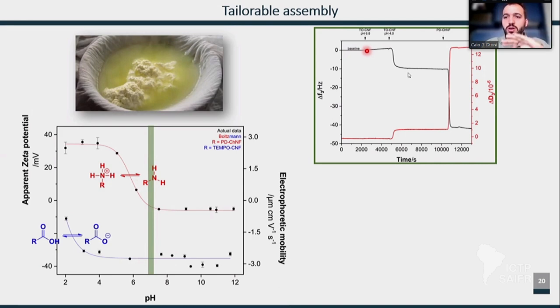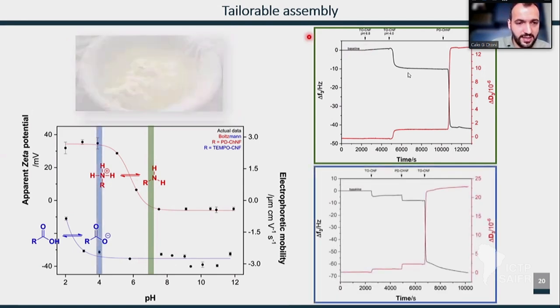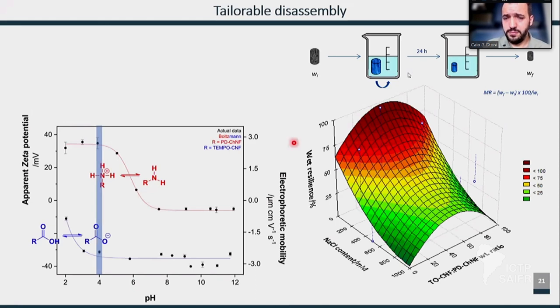How? Removing salt or switching pH. So if we do the same system at pH 4, for instance, then the cationic blocks are going to be active, protonated, and the anionic blocks are still deprotonated. So you have like plus 35, minus 35. It's qualitative, you know, but then complexation takes place. You can see here that when the pH is shifted to 4, I hope you can see it, frequency changes and complexation takes place. But the beauty is that it's reversible. And this is important for recyclability. The same thing that I want to complex, I want to decomplex in a controlled fashion, right?